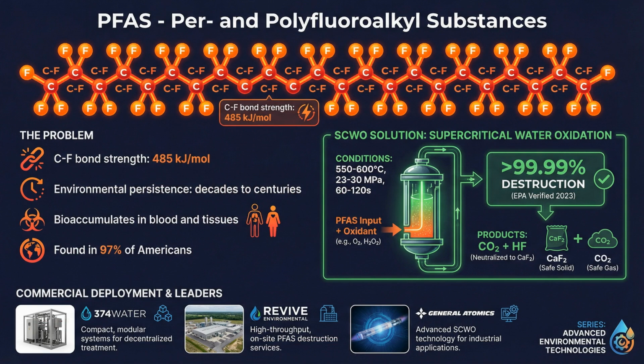One of the most important applications of SCWO is destroying PFAS, the per- and polyfluoroalkyl substances often called forever chemicals. These compounds have carbon-fluorine bonds at 485 kilojoules per mole, among the strongest bonds in organic chemistry. They don't break down naturally, they bioaccumulate, and they're found in the blood of 97% of Americans. SCWO at 550 to 600 degrees Celsius for 60 to 120 seconds achieves greater than 99.99% destruction of these compounds, verified by the US EPA in 2023. The fluorine is released as hydrogen fluoride and immediately neutralized to calcium fluoride, a stable mineral. Several commercial facilities are now operating.